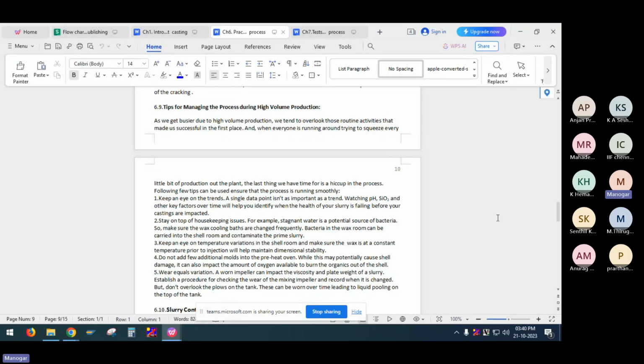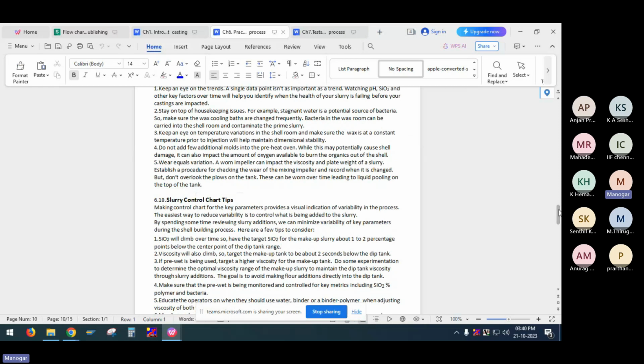Keep an eye on the temperature variations in the shell room and do not add a few additional molds into the preheat oven. This may potentially cause shell damage. It also impacts the amount of oxygen available to burn the organics out of the shell. So if there is no space, don't put extra shells in the firing place.